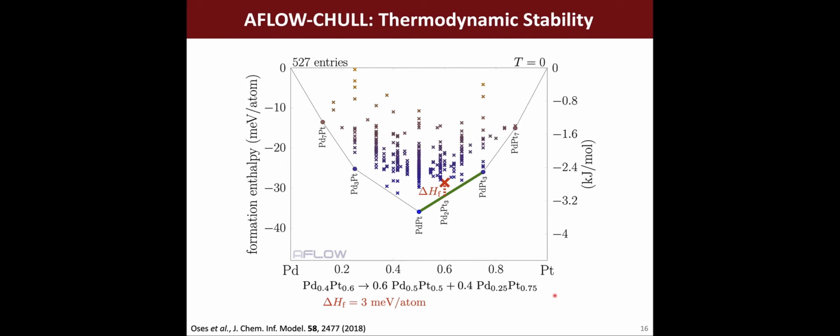But that distance is also an important metric, that energetic vertical distance from the point to the facet below it. That also tells me the decomposition energy of the reaction. So what is the driving force for this reaction? You can imagine that if this distance is very large, then the products are going to be heavily favored over the reactants, so it's really going to want to decompose. In this case, the distance is very small.